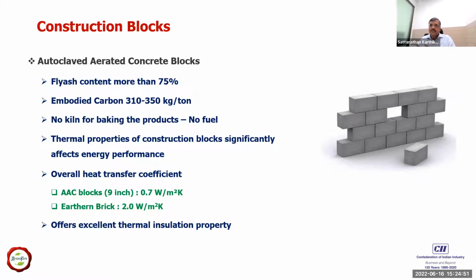Another aspect is that there is a lot of thermal insulation property attached to this, because it is porous and lightweight, so the U value of this brick is much better than a red brick. For example, in the case of a red brick, the U value is about 2 watts per meter square degree Kelvin. In the case of AAC block, it is as low as about 0.75 or 0.7 watts per meter square degree Kelvin. That means a wall constructed with AAC blocks will allow one third of the heat to pass through.